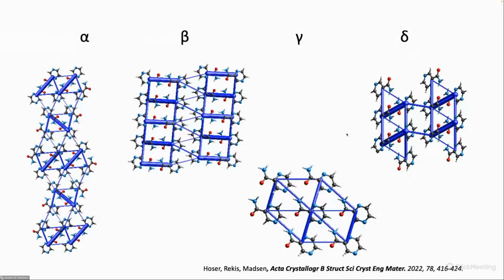So let's take a look at these different forms of pyrazinamide. Here we have some energy diagrams showing that they are quite different. There are some similarities though. So the alpha and the beta and the delta form all form these dimers of pyrazinamide molecules that are then packed in different ways. So we have these very strong interactions between the dimers here. Whereas in the gamma form, it is quite different. Here we have more like different, weaker interaction energies that add up to more or less the same energy as what we have for the other forms. If that didn't happen, of course, we wouldn't see the gamma form. It wouldn't have been a stable form at all.